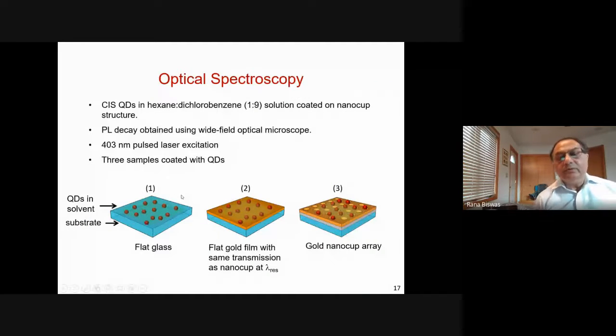So to show you the way this was done experimentally, you had these copper indium sulfide quantum dots in solution coated on nanocup structures, and the photoluminescence decay was measured using a wide field optical microscope using a short wavelength 403 nanometer pulse laser excitation.